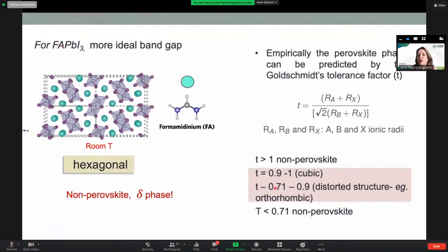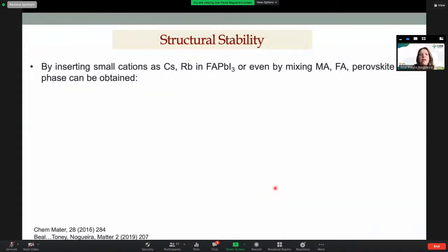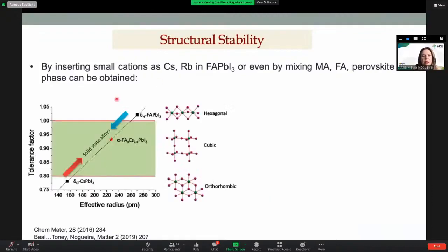So in order to have a cubic phase, the phase that's actually proper for photovoltaics, you need T between 0.7 and 1. How can we do that? We can insert small cations like cesium or rubidium into FAPI, or even mix formamidinium and methylammonium. For instance, FAPI and formamidinium-only or cesium-only compositions are non-perovskite phases. But if I take FAPI and put in a little bit of cesium, I can push down this tolerance factor to fit between 0.8 and 1.